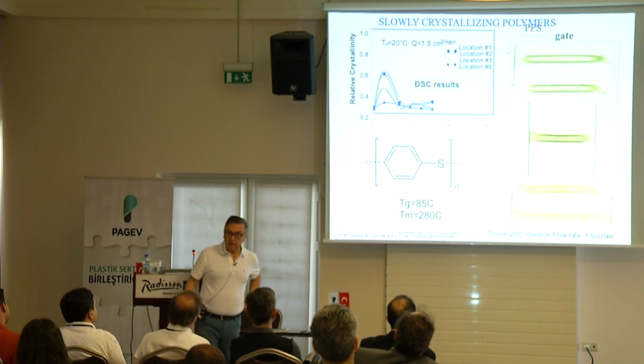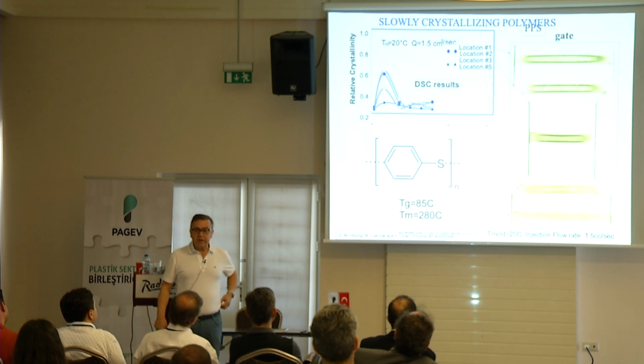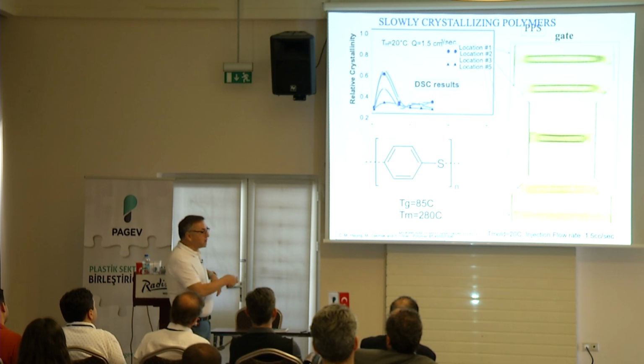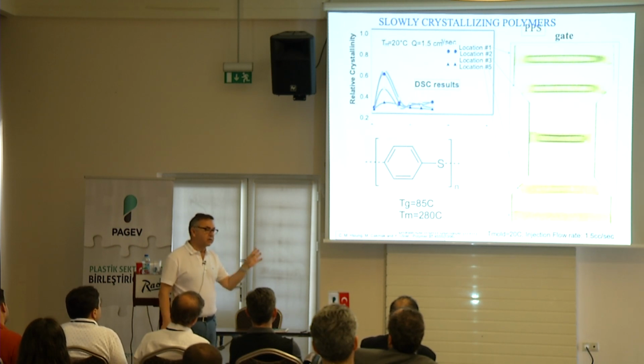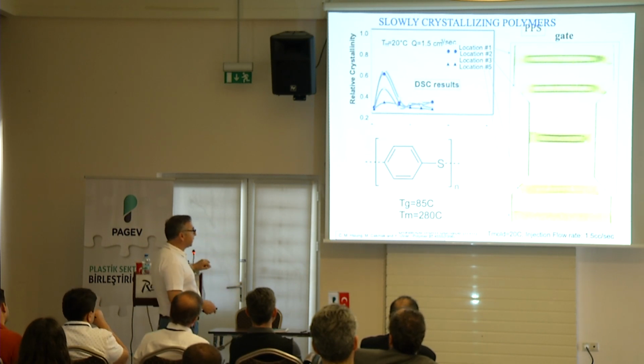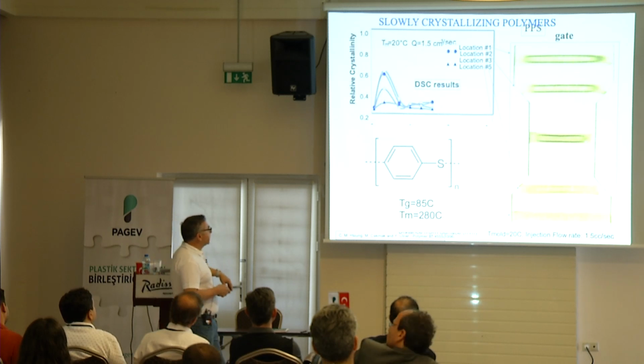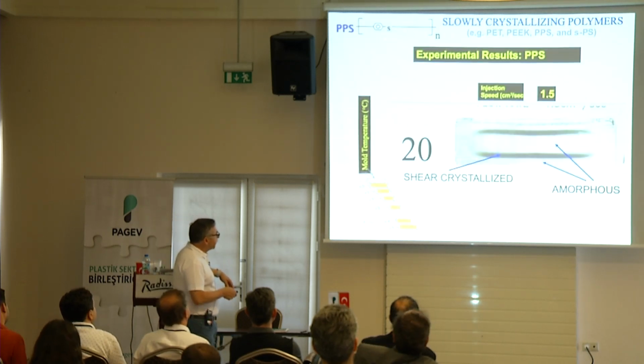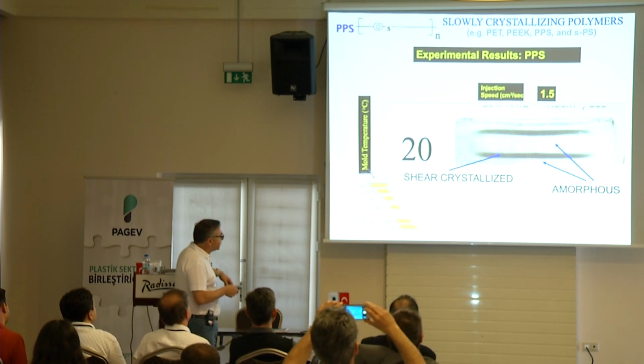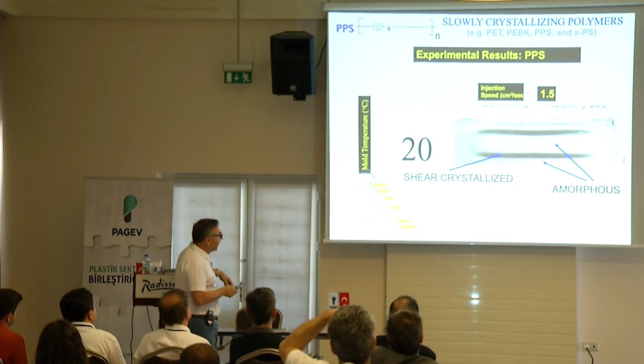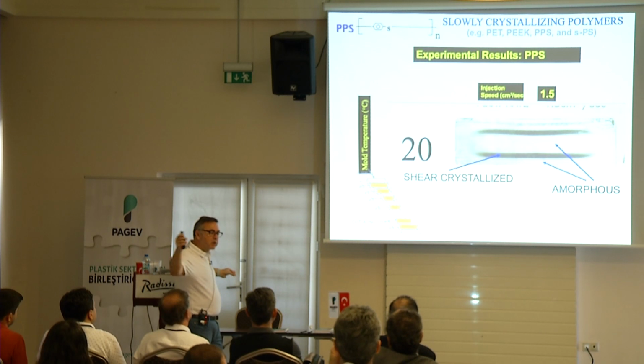How can that be? We already said polymers are poor conductors. If the polymer is a poor conductor, the inside must crystallize, right? If it's polypropylene, it will crystallize. But for these materials, the thermal crystallization is turned off. Because it's turned off, you have an interesting shear effect. So what we have is an amorphous skin, an amorphous core, and a shear-crystallized intermediate layer. And it's all coming from just stretching the polymer chains.